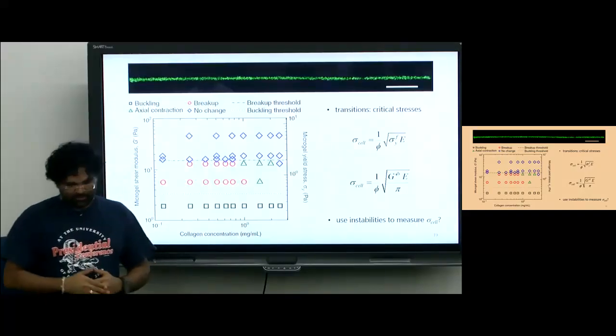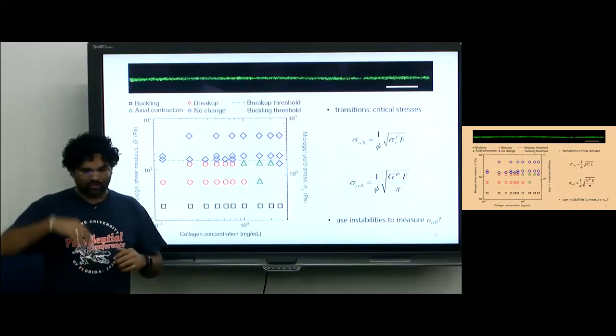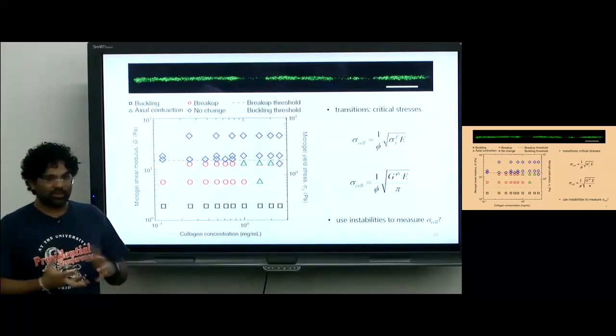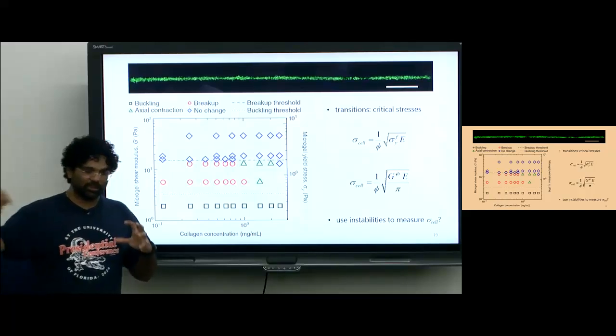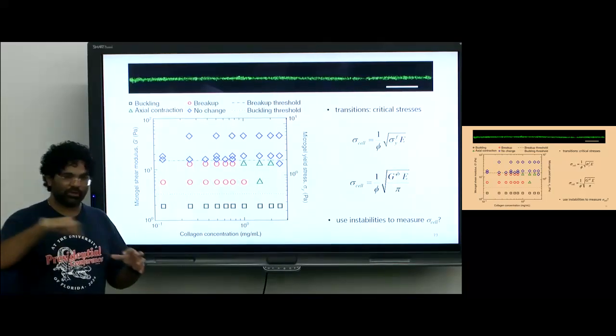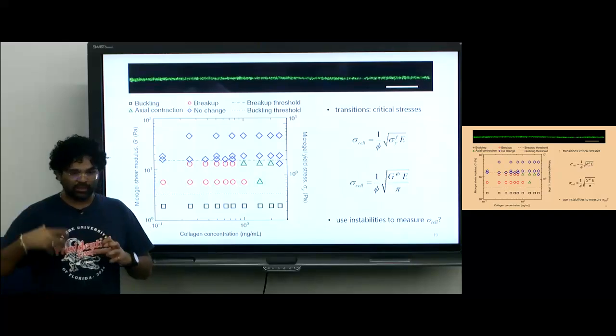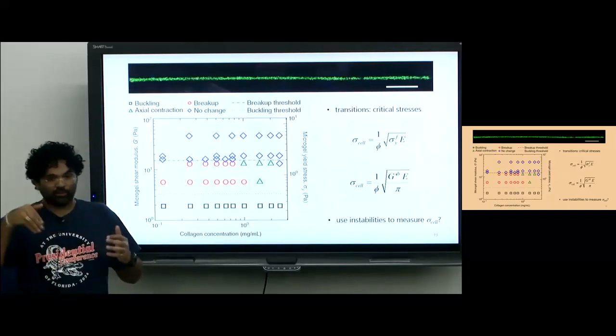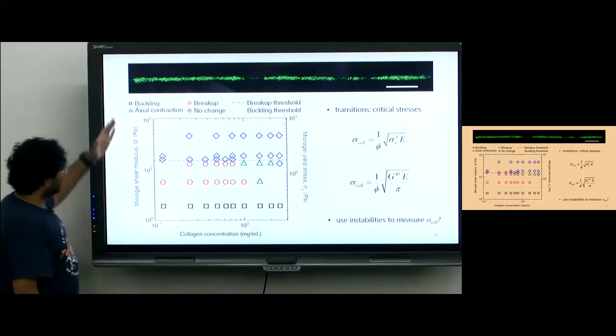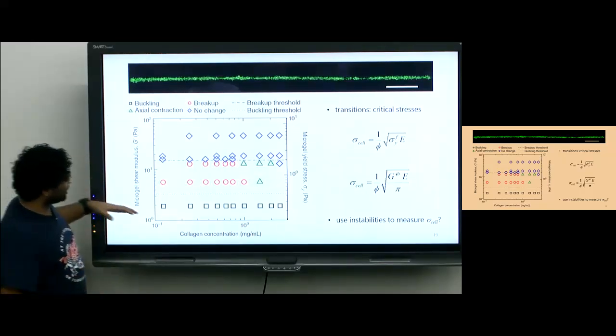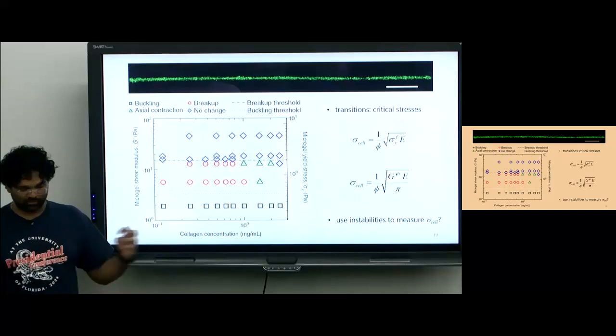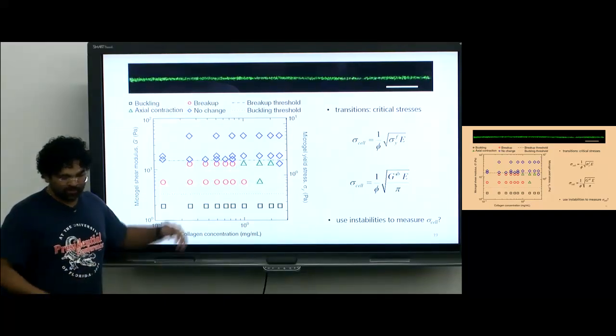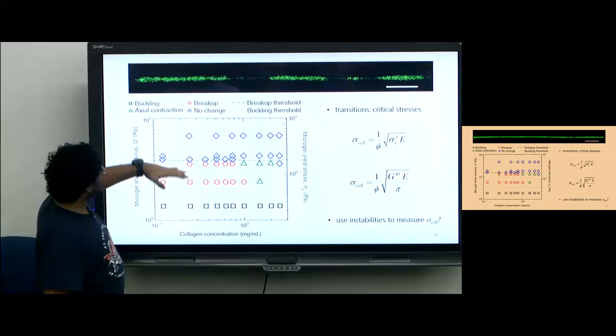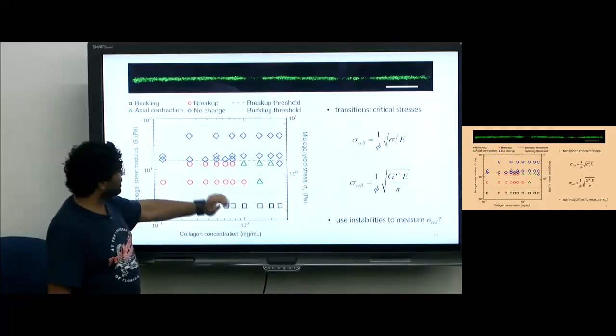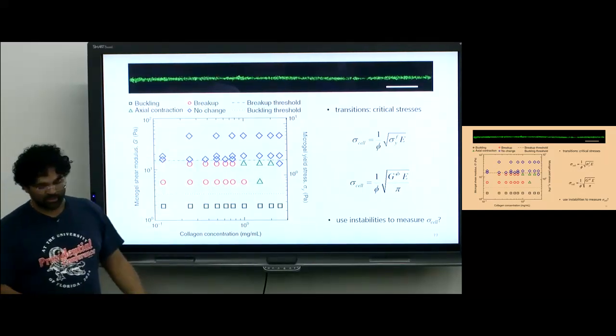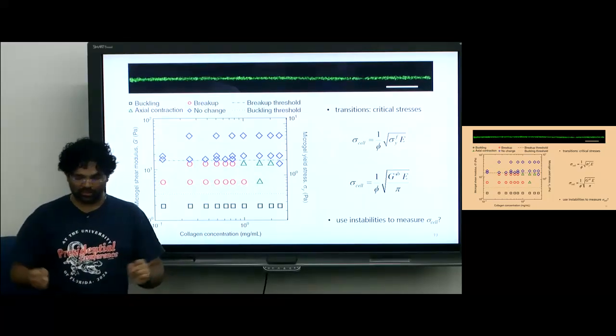And then from here, they also looked at varying the yield stress of the support material. We talked about yield stress as one of the criteria, right? Like the support material yield stress needs to be low enough that you can print into it, but not so high that it'll form crevices and stuff like that. So you can also map out the shear modulus of your surrounding material versus the concentration of the matrix in your beams. And again, a threshold was detected for what shear modulus and what collagen concentrations are needed in order to get stable structures and in order to not have these printed structures buckle.